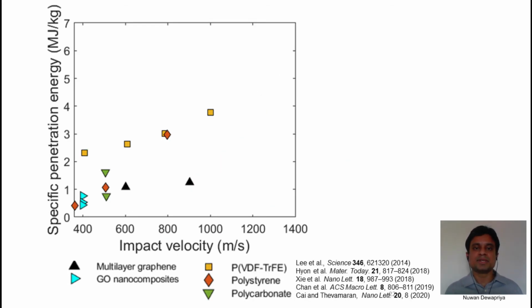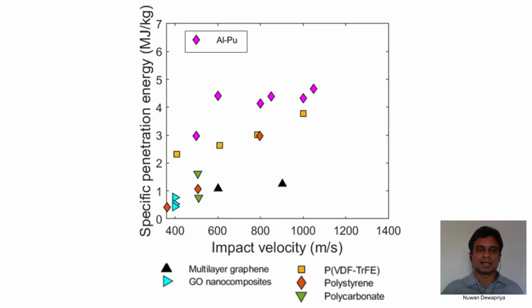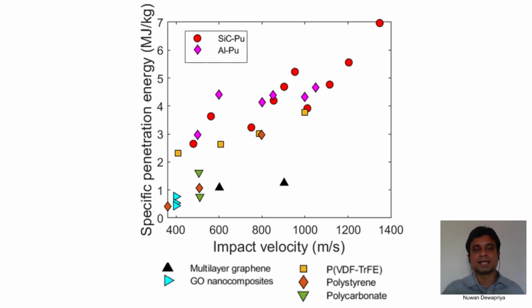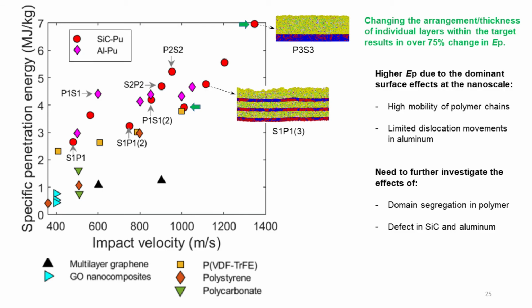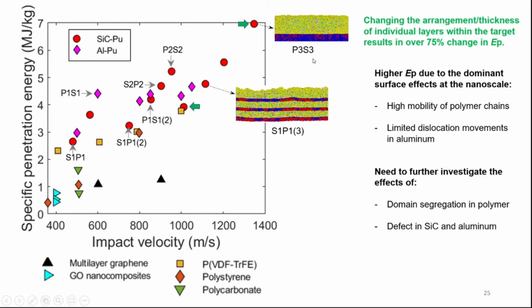These are the EPs of different nanomaterials measured using microprojectile impact tests. Here EPs of aluminum polyurea layers are shown. Here EPs of silicon carbide polyurea layers are shown. We can see that the P3S3 target has the highest specific penetration energy, and we can change the specific penetration energies by changing the thickness and the arrangement of individual layers within the target.